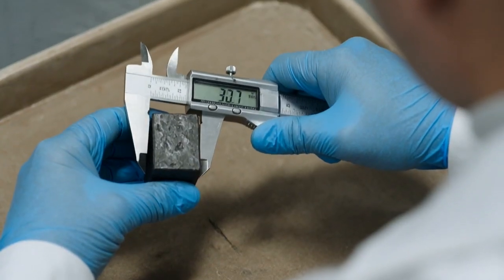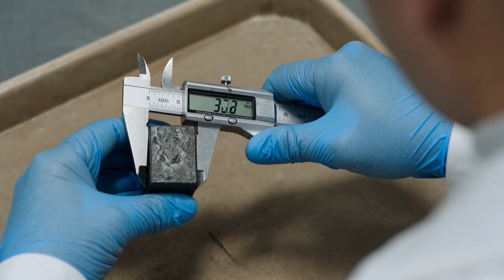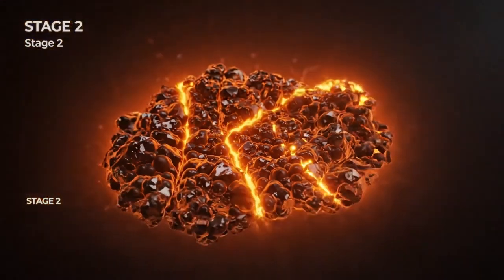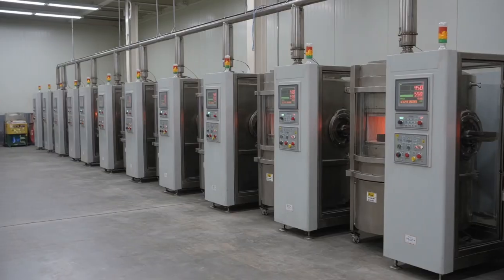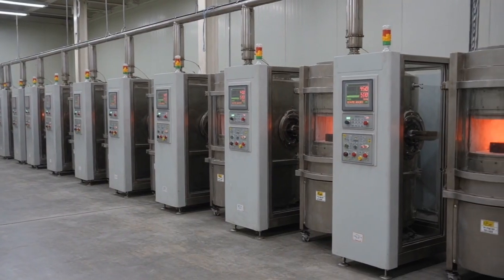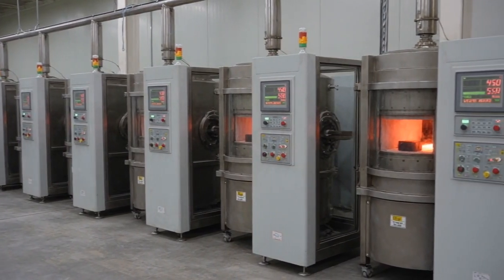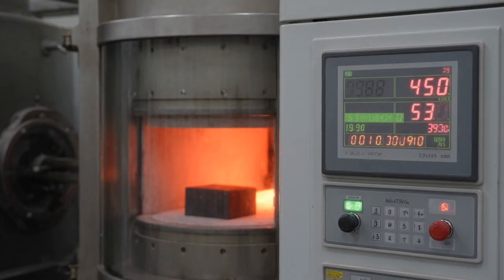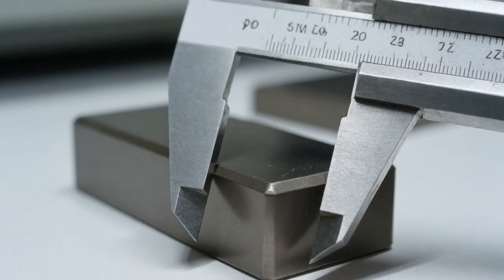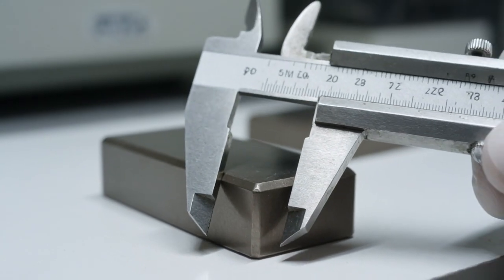After sintering, the magnet undergoes 2 stages of tempering, precise heat treatments at lower temperatures. The first stage at around 900 degrees Celsius for 3 hours. The second at around 450 degrees Celsius for 4 hours. Each stage adjusts the microstructure at the atomic level, maximizing coercivity, the magnet's resistance to losing its field.